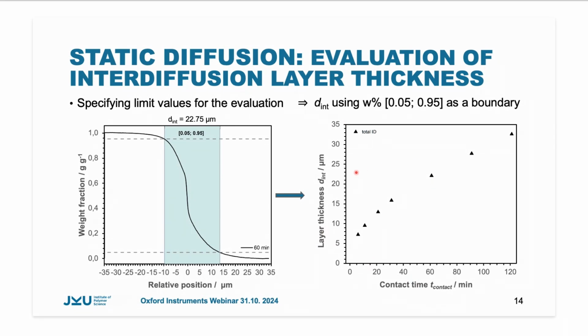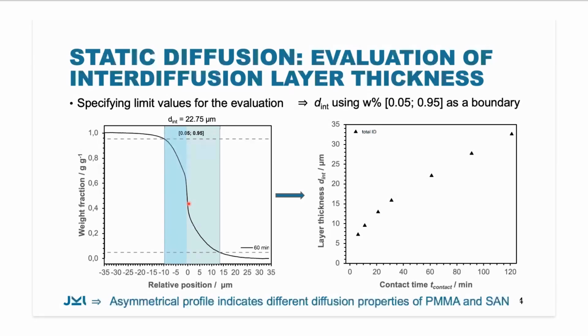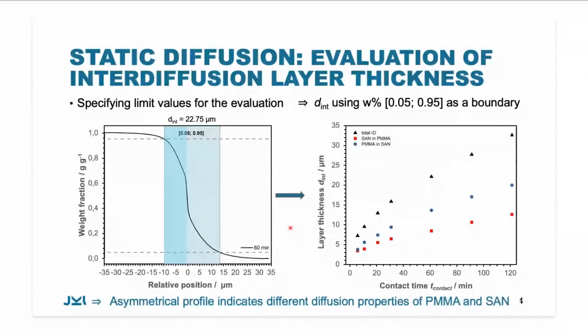Now we can look in a little bit more detail at our profile. And even if we have here our 0 position, what we see is that our interdiffusion layer is asymmetric. The profile is smaller on the left than on the right. This indicates that we have different diffusion properties of PMMA and SAN. And we also analyzed the layer thickness for the individual layers, and we see, when we assume that on one hand SAN is diffused into the PMMA and the other way around, that SAN has a lower diffusion property than the PMMA.